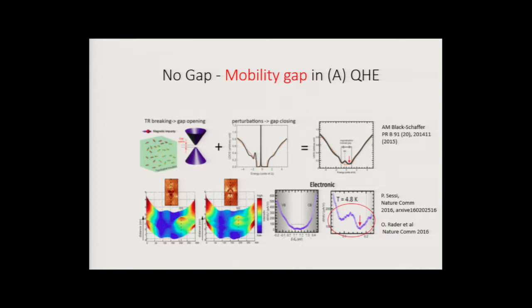And then on top of it, if I recall that I told you that any defect inside the Dirac material produces resonance, what I need to do is solve the problem where not only have I magnetically opened the gap, but I have to look at the scattering off this impurity site. So you cannot bring a foreign atom, like an iron atom, into the matrix of the crystal without accounting for the fact that it has to scatter off this site. So it's a foreign atom. In addition to magnetic exchange interaction, there is a potential scattering term. And this potential scattering term will generate this impurity resonance. As long as the potential part is larger than the exchange, this resonance will always come.